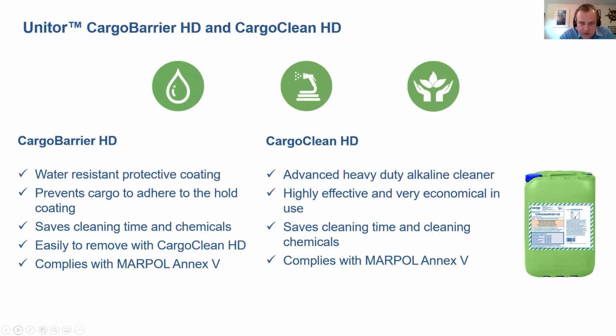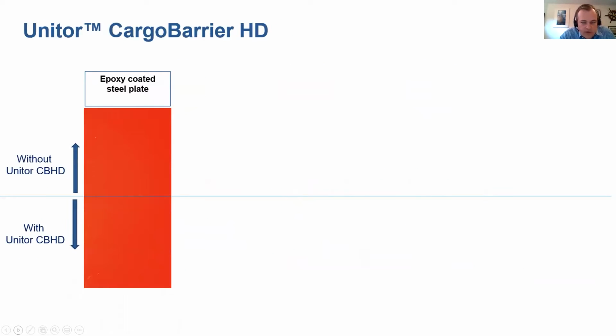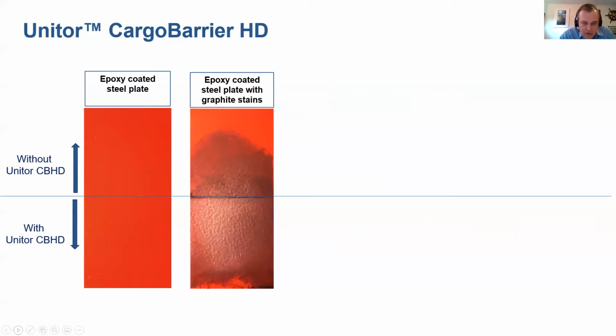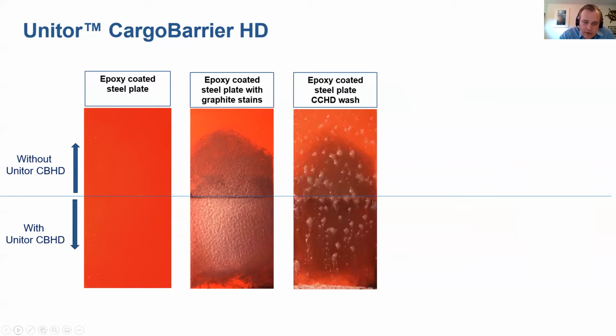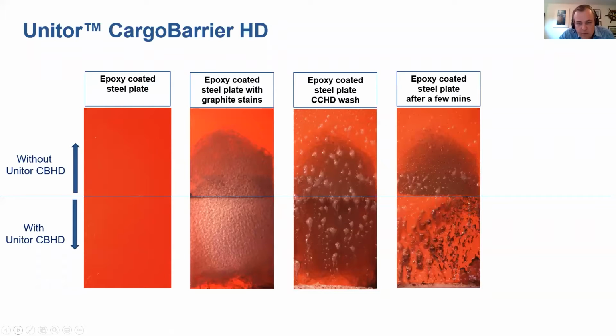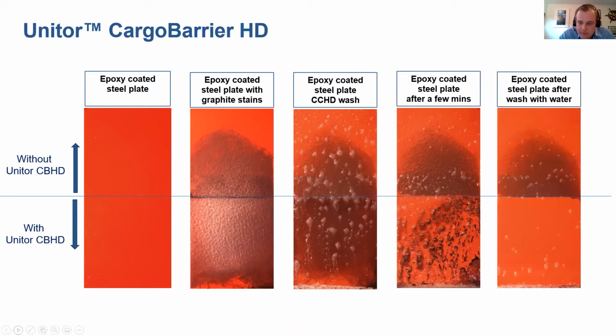And to show you an example of how this could look, we must imagine we have an epoxy steel plate. We cover the lower part, we apply Cargo Barrier HD, and on the upper part we don't. Then we used graphite powder because it's very fine, it goes into the coating pores, and we rubbed it onto the surface. Then you use Cargo Clean HD in 10% and apply it on the steel plate, and let it soak for a couple of minutes. We can see already on the lower part that the cargo barrier temporary film is dissolving and taking the stains and contaminants with it. Then when we do the final rinse with fresh water, we can see that the lower part is taking off the cargo barrier film, but it's also taking off the contaminants on the surface.